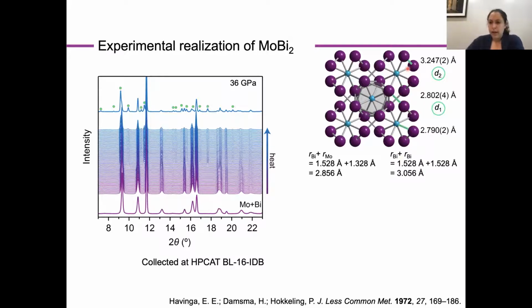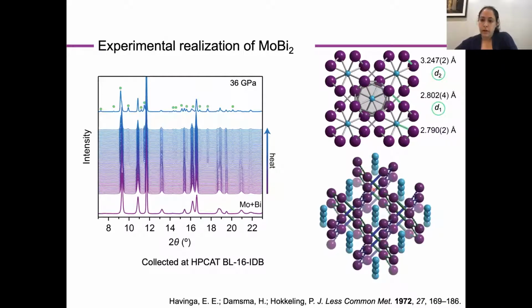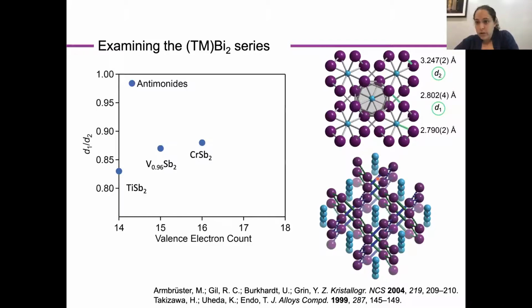And so that was somewhat surprising because another way to think about the structure is from this view here, which we get by rotating the structure about 45 degrees to the right and tilting it into the plane of the screen. You can see that in this case, the bismuth form planes in which you have interlocking hexagonal nets. But because of the distortion of D1 versus D2 in our structure, we've broken up those hexagons such that we're left with stacked bismuth dimers. And as I mentioned, this is somewhat unusual for the structure type, but it's not unprecedented. It has been seen before for the antimonide versions of the structure, so the element that's directly above bismuth in the periodic table. And given that similarity of where we're looking on the periodic table, I was wondering if something electronically driven was occurring.